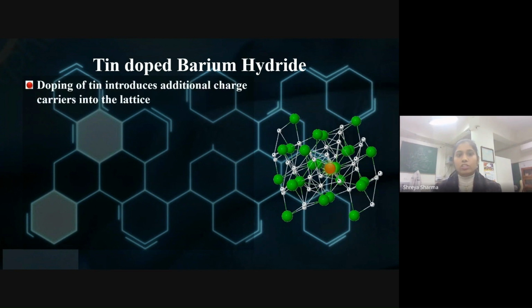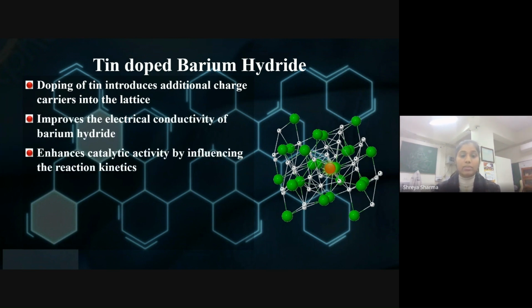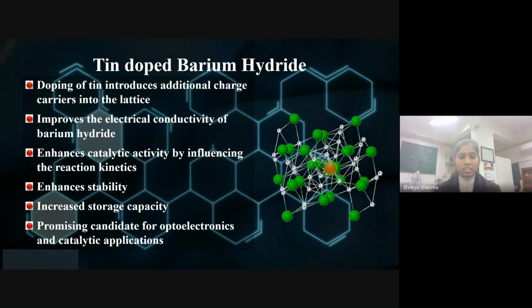Doping of tin introduces additional charge carriers into the lattice, and it improves the electrical conductivity of the pristine barium hydride, enhances catalytic activity by influencing the reaction kinetics, and it enhances stability also. It increases the storage capacity of the material. And thus, due to these enhanced properties, it can be a promising candidate for optoelectronic and catalytic applications.